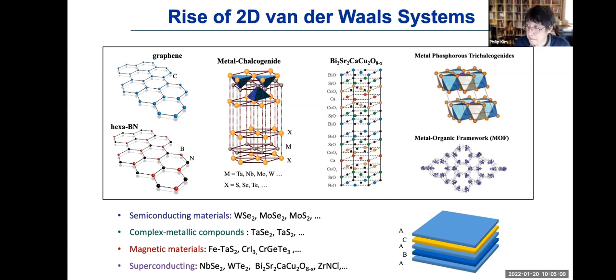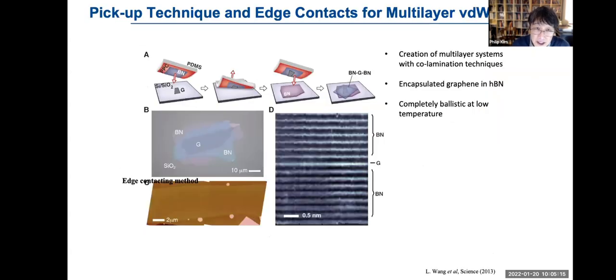It is not only a simple PowerPoint demonstration. Over time, people indeed demonstrated such heterostructures can be built. You can try to grow these materials, but you can also simply break the material, as shown in this example, down to a monoatomic layer. And one by one, you can pick up the materials using the weak van der Waals force between them. You can come up with stacks of van der Waals material by design, deciding which order and sequence you pick up the materials. You can quickly build up an arbitrary sequence of van der Waals system.